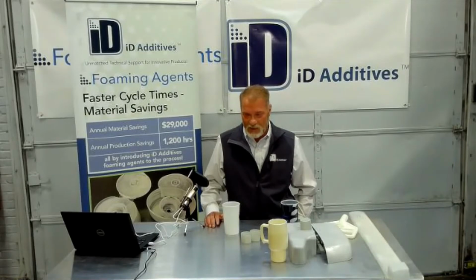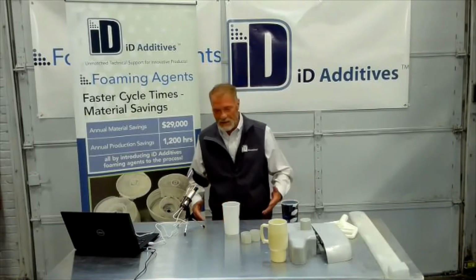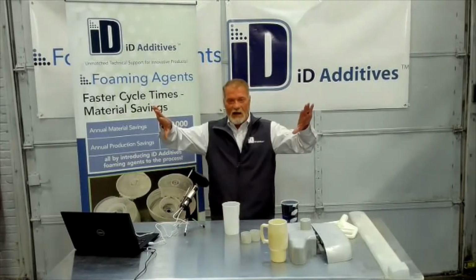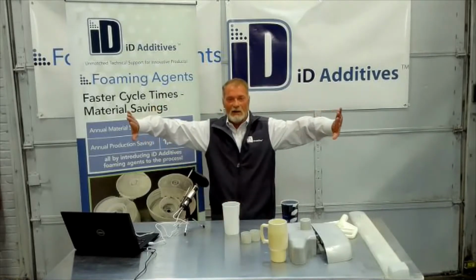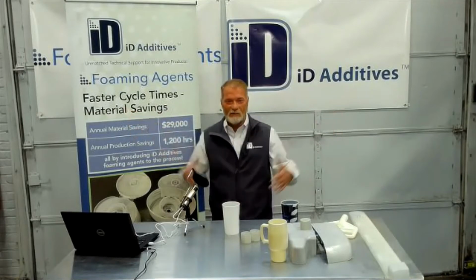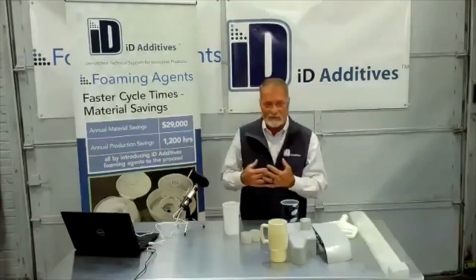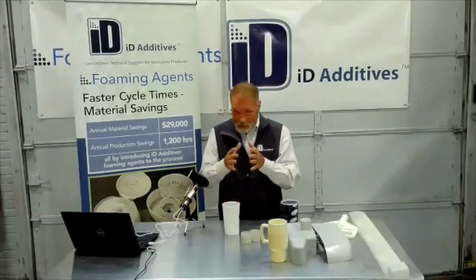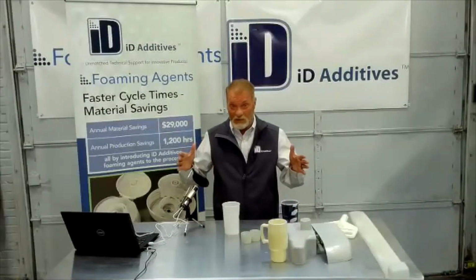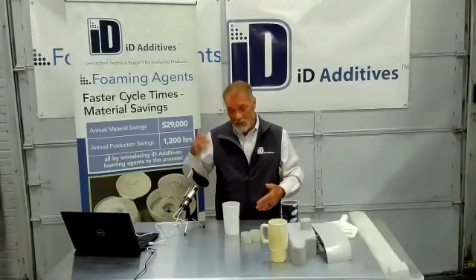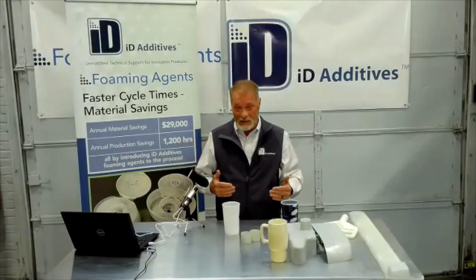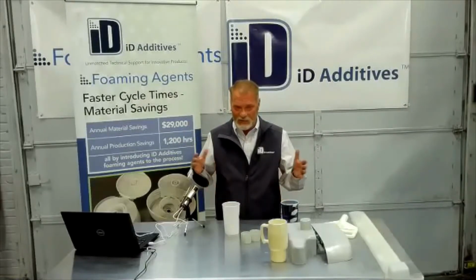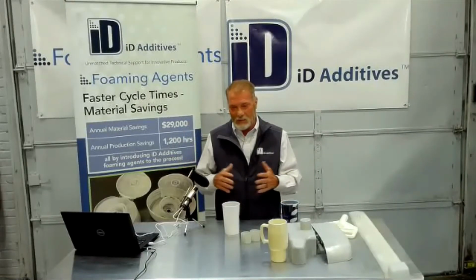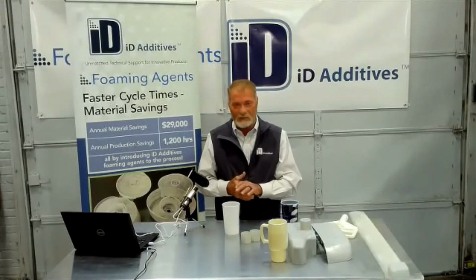When the parison drops and you're using, let's say, 90 PSI and you're blowing it out, well, you're packing the part out as you're blowing it. So you're going to find that when the parison drops, the viscosity changes to where it blows out much easier. You don't need those pressures. We went from like 90 to like 38 PSI, low pressure. That's huge. Any more than that, you'll pack the bubbles out.